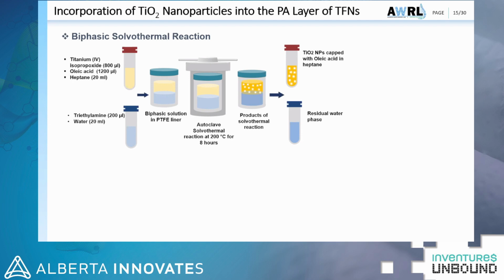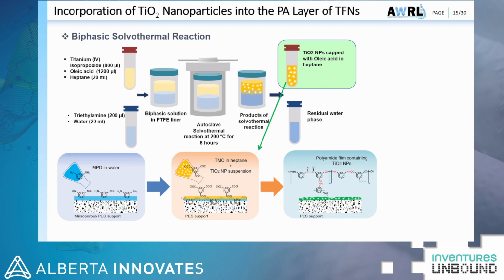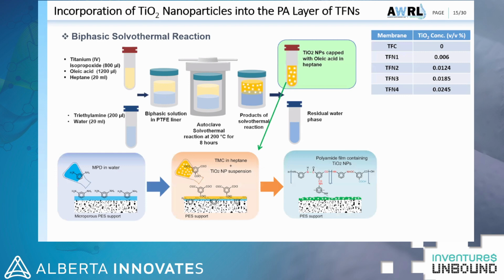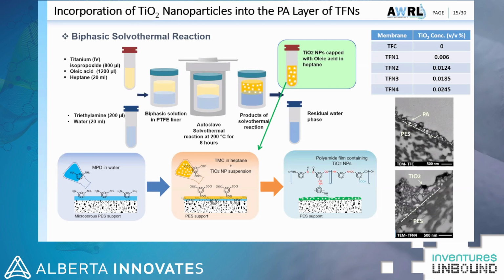In this technique, the solution containing titanium isopropoxide, oleic acid and heptane was first mixed with the aqueous solution of triethylamine. The reaction occurred in the autoclave at 200 degrees C, and the supernatant, the top liquid containing the TiO2 nanoparticles capped with the oleic acid, was collected for the IP reaction. TMC was added to this solution, and after the IP reaction, nano-sized TiO2 nanoparticles were entrapped in the polyamide matrix. We synthesized four different types of thin film nanocomposite membrane with different loading of nanoparticles and tested them. The TEM cross-sectional image confirmed the presence of these nanoparticles. So you can see the TiO2 on the top active polyamide layer.